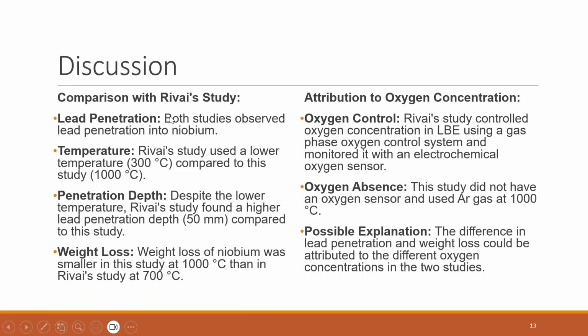Comparison with the previous study. For lead penetration, both studies observed lead penetration into niobium. For temperature, the previous study used a lower temperature, 300 degrees Celsius compared to this study's 1000 degrees Celsius. For penetration depth, despite the lower temperature, the previous study found a higher lead penetration depth, 50 millimeter compared to this study, and